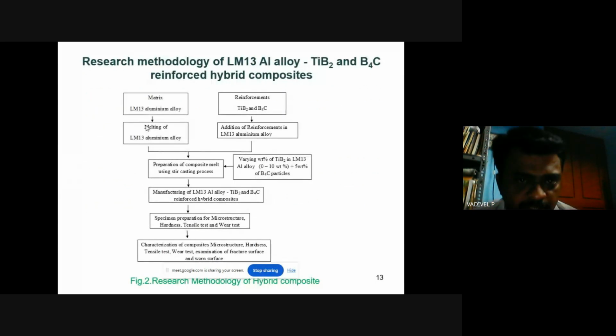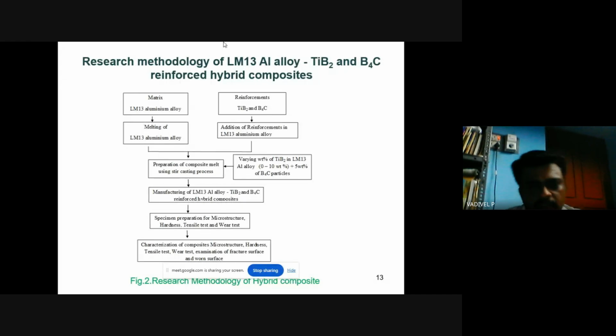Here is the research methodology chart with the LM13 aluminum alloy and boron carbide, which in general we call ceramics. First we prepare the metal matrix of aluminum LM13 alloy, and we have melted the aluminum alloy, and the reinforcements were preheated and added to the LM13 aluminum alloy. After that, we prepared the composite melt using the stir casting process with varying weight percentage of 0 to 10 weight percentage of titanium diboride and 5 weight percentage of boron carbide. After the mixing is done, the manufacturing of the composite has been completed.